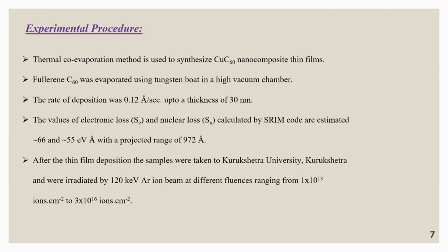After synthesizing our samples, we took them to Kurukshetra University for ion irradiation with a 120 keV Ar ion beam at different fluences ranging from 1E13 to 3E16.